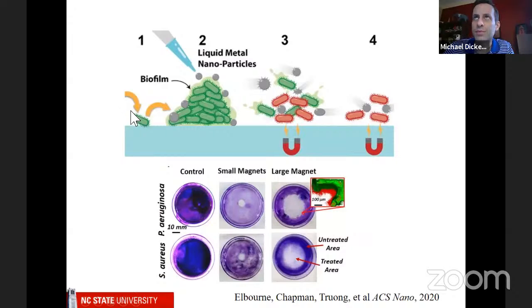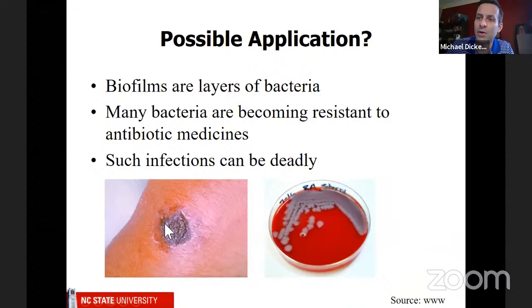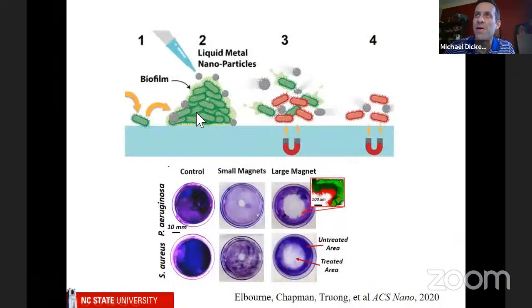So what we do is, these green things are the bacteria. These are, if I go back, the gross looking things that are on the skin, and they form a film. And that film, like I said, is like a barrier. It prevents oxygen and nutrients from getting into your wound to keep it from healing. So we put these particles, and then we apply a rotating magnetic field. So the magnet just spins, and those particles start to become spiky. They become rods. And again, this is another thing we don't really understand. It just happens to work really well. These will kill the bacteria, which now show up as red, and eventually all the bacteria goes away.